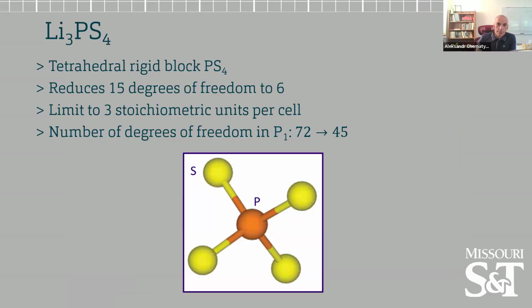This is the example of the system that we're going to look at first. Again, this is the test of the method rather than prediction at this point. So there are well-known results for what the ground state and metastable structures are. I will show them towards the end of the discussion on the system. Here I have a tetrahedral block, which is shown in the picture here. The phosphorus atom is in the middle and the sulfur atoms are spread around. So one can make a primitive count and convince themselves that 15 degrees of freedom are being reduced to 6 in